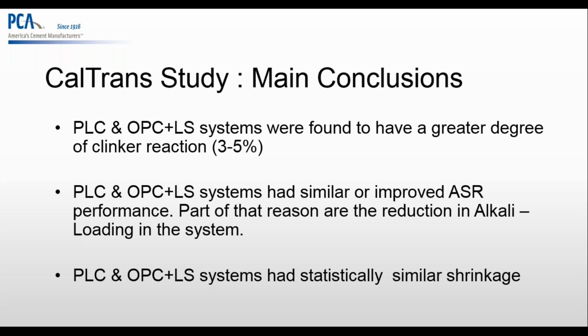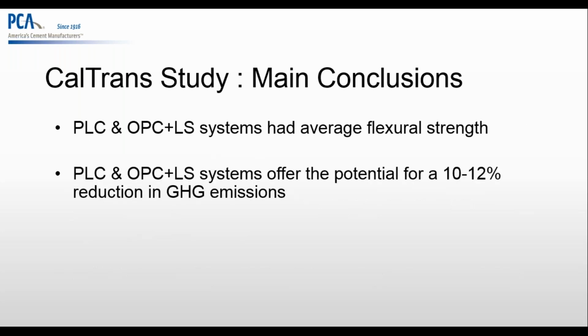That's very important. When I say ASR, it is alkali silica reaction, and this is very important if you're doing business or if you're doing an FAA project, right? They're all over the alkali silica reaction, right? And this is because the alkali loading in the system is reduced, right? There's less clinker in the PLCs. On the shrinkage side, it was pretty much similar. The flexural strength was average. It was pretty much the same, but they concluded that overall everything is pretty equal, and we can get a reduction of GHGs in the rate of 10 to 12%.